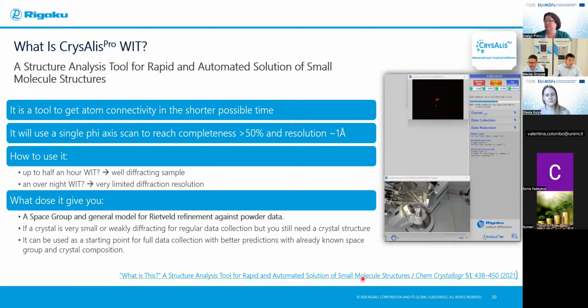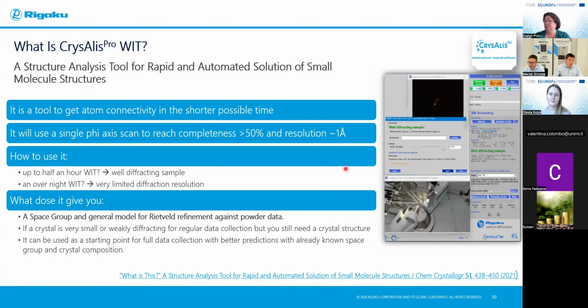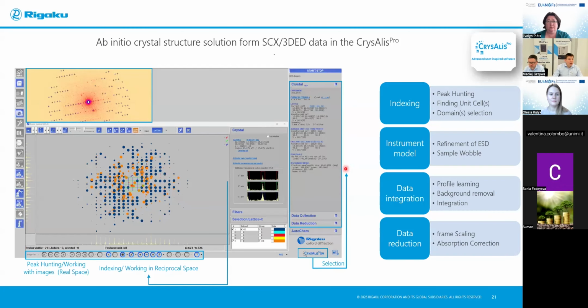There is a publication reference at the bottom, but basically it's just a data set that goes to 50% completeness, and the target is 1 angstrom. That's the requirement to solve the structure with direct or intrinsic phasing methods. And as I mentioned, this is the preferable way: keep this method at the beginning and get the structure to refine against your powder, because this is the gold standard in research to get the structure out of your material.